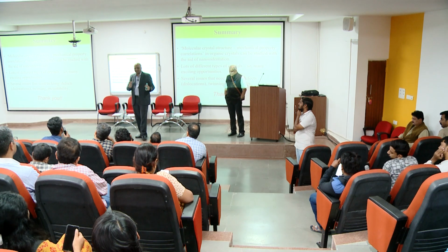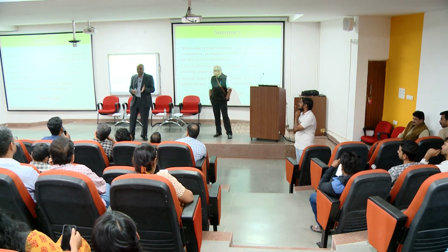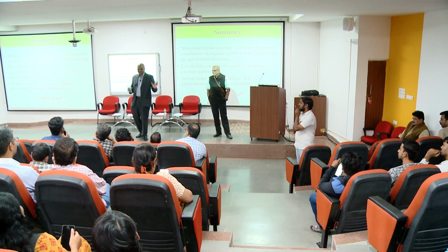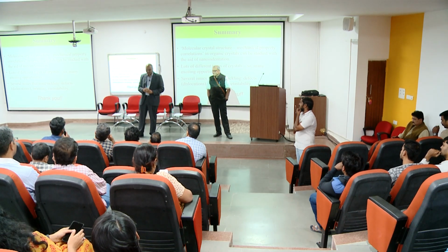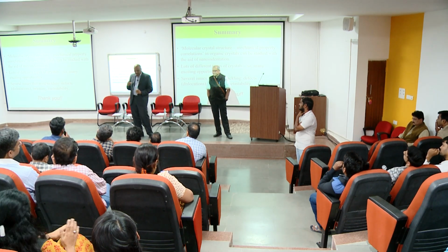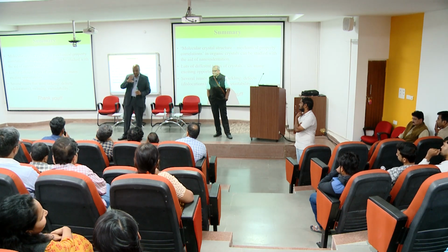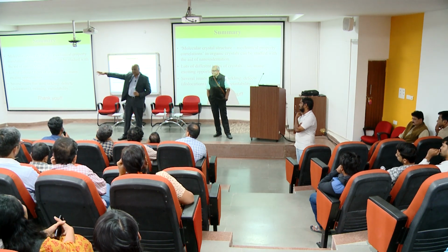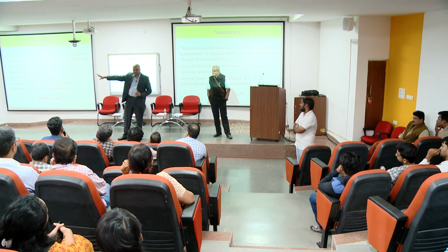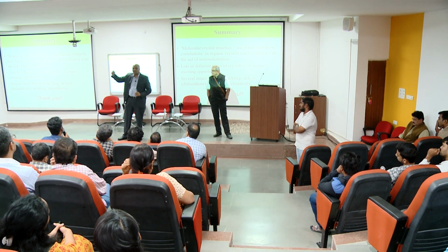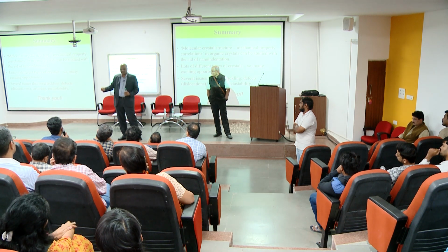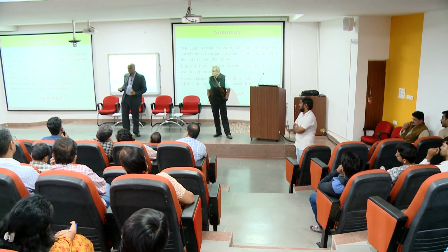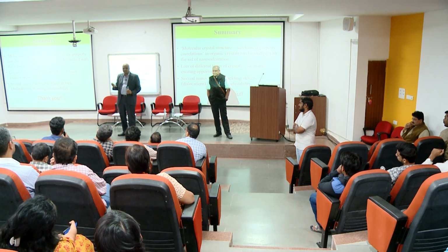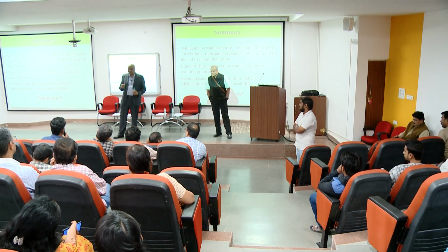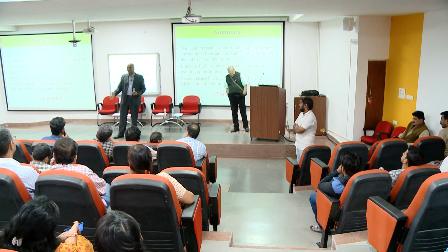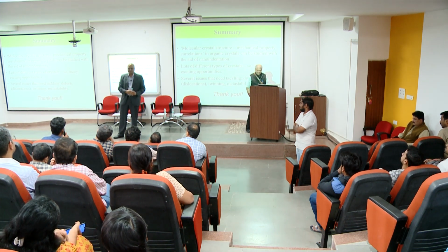By the way, my actual bread and butter is breaking materials. I do fracture and fatigue; that's my thesis, and that's what I actually do. For a crack to form in a material, even the most brittle material, take a window glass, the most brittle, with 0.5 MPa root meter fracture toughness, you need a critical energy density that is required to drive the crack. These are generally plastic materials, and the energy that we put in through nano indentation is, in quantity, abysmally low. So it will never drive it to cracking.